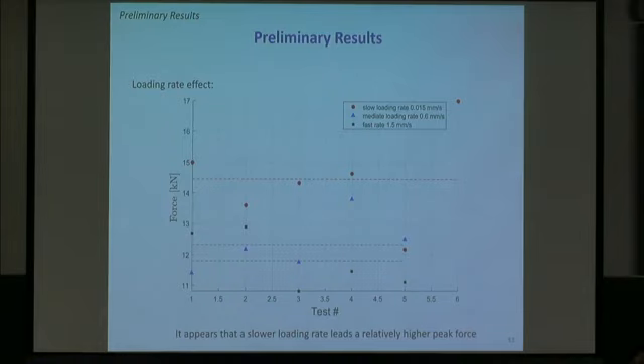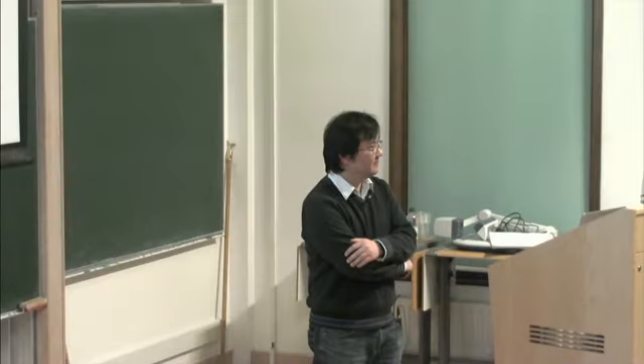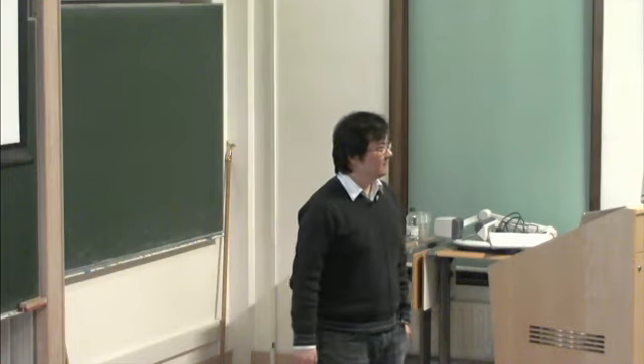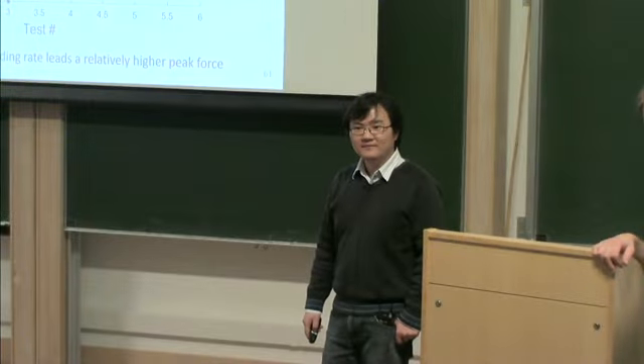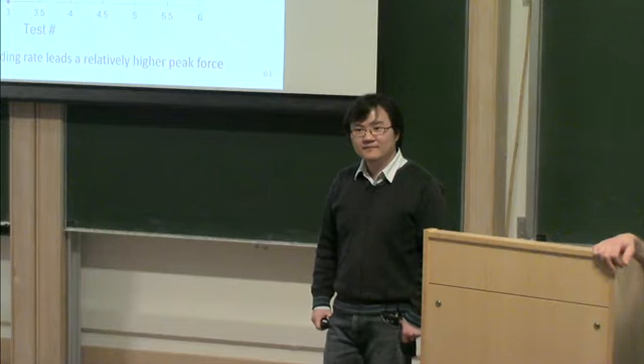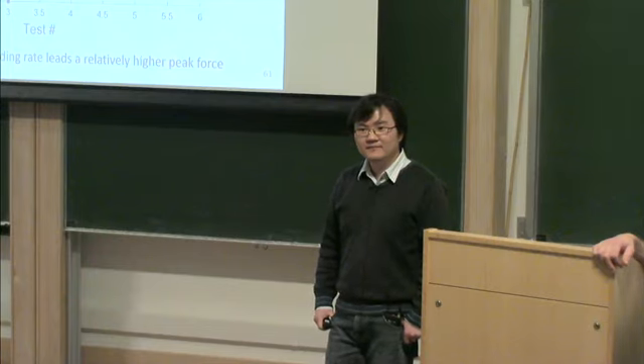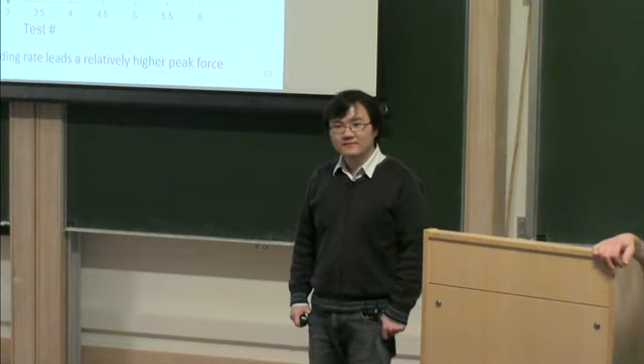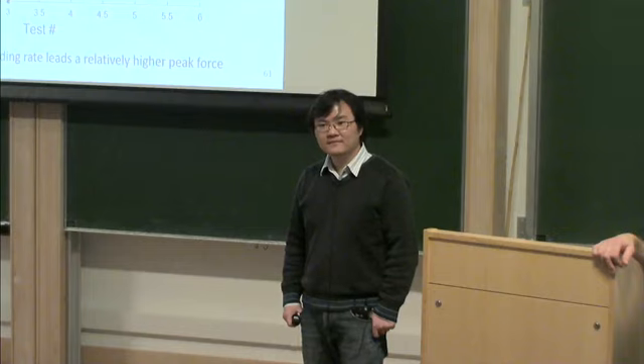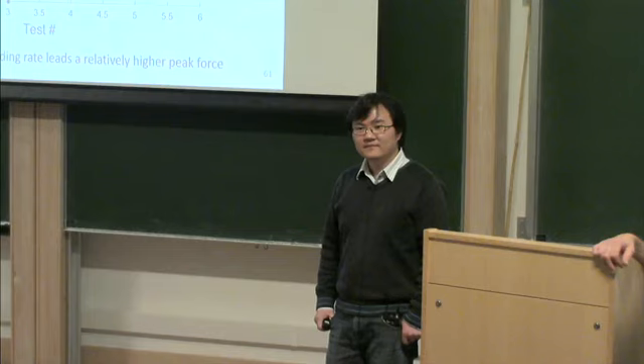Chris? So sort of following up on that, actually, I've done hundreds of loading rate tests with snow samples in bending, and I see the same thing. I see higher peak loads for slower loading rates, and it is consistent and it is statistically significant. And it seems to me that the answer does lie in some sort of, at slower loading rates, you've got a little bit of creep deformation at the crack tip. It's competing with the sort of crack growth, kind of like you described earlier, Erlen. I think that's the explanation for why you're having to put more energy in, because you're dissipating a little more at the crack tip at the slower rates.